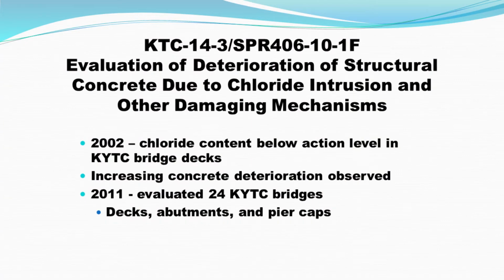Back in 2002, the Kentucky Transportation Cabinet looked at a handful of bridge decks, primarily because we had used what we classified as a AAA concrete mix design in the bridge decks, and there was some surface crazing and surface cracking early on. We wanted to look at how those cracks were allowing propagation of chloride ion into the deck. That study in 2002 showed very little chloride ion penetration into those decks.